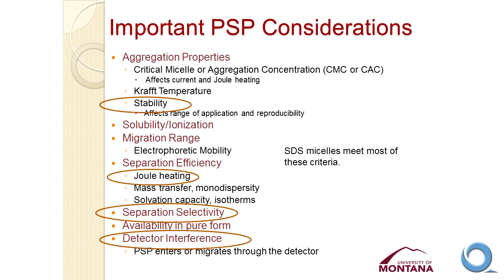SDS works really well with UV detection, but it is not compatible with mass spec detection. And mass spec detection is really important, of course, for pharmaceutical analysis and also for forensic analysis. And then finally, the stability of the micelles is a bit of an issue. When we start adjusting the conditions, suppose we add organic solvents to adjust the separation conditions, then the thermodynamics of micelle formation change, the structure of the micelles changes, and even the existence of the micelles can be in doubt. So that's always been a problem with SDS micelles.